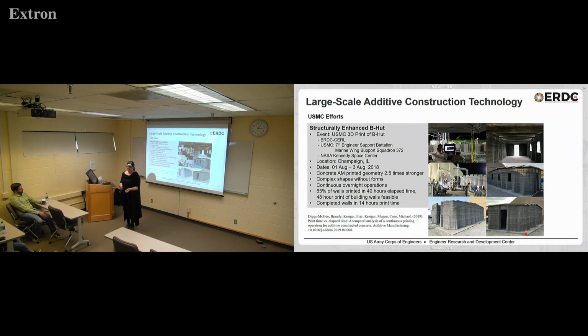So people that use rapid setting materials, what'll happen is if they go through and print a layer and it's already cured before they come back and print another layer on, that material will not bind to the next layer as much. And so you have a weak spot. If you say, leave your material and come back a week later, it's the same kind of thing. You have a cold joint there where you wouldn't have it if you printed it continuously. And so this building is really the first in the world that was printed in a continuous fashion. And that is a huge push forward for the 3D printing construction field because it shows that we don't need to be limited by that time per layer mindset.